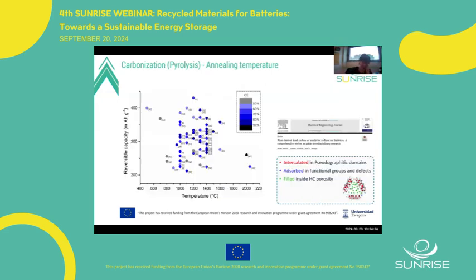Taking this into account, there are different studies in the literature. Here is a summary using different carbonization temperatures, making pyrolysis of the biomass to produce hard carbons. As you can see, depending on the biomass you choose and the temperature you select, there are different reversible capacities of the active material, so we need to optimize it for each kind of biomass.